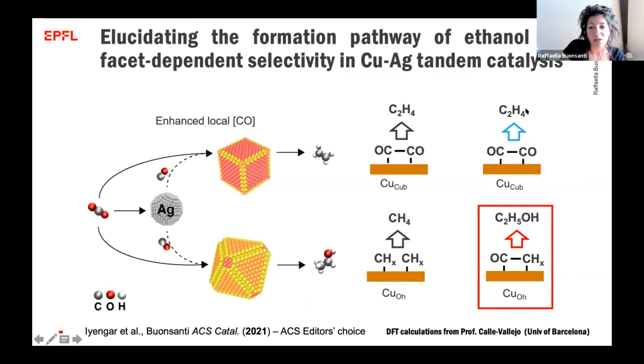And this finding actually suggests that the formation of ethanol occurs via CO-CH coupling because the octahedra, for the fact that they are selective for methane, possess a surface which is enriched in CH intermediate, which then reacts with the CO and eventually generates ethanol.